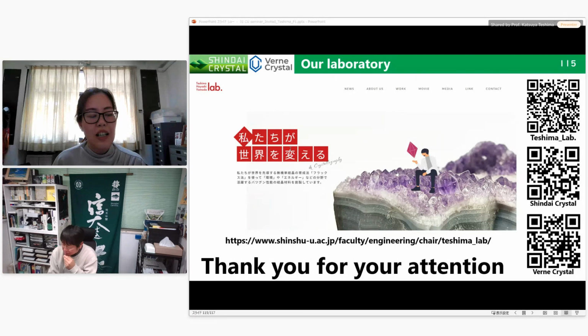In the case of flux-grown crystals, there are very good lithium-ion paths in their bodies. So lithium ions move very fast, and they showed very high performance compared to commercial powders. You can choose the preferred orientation, where it mainly has the preferred direction of lithium movement. Something like that. And crystal facet is very important.